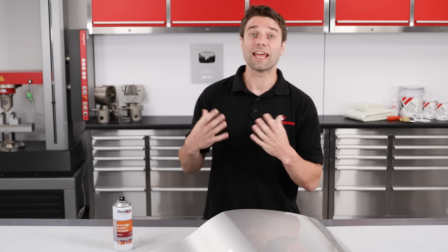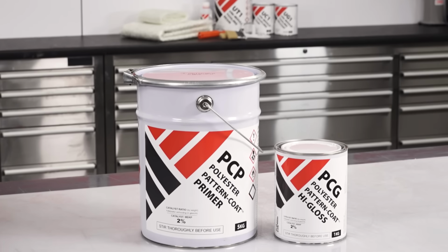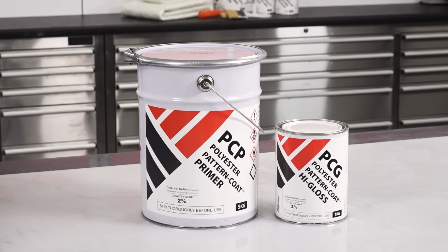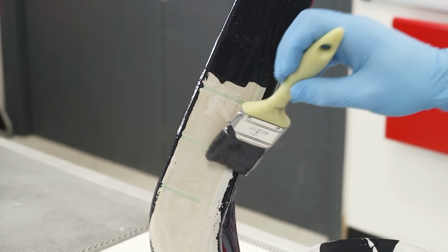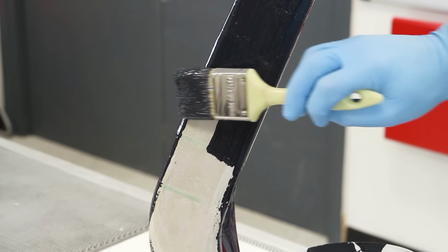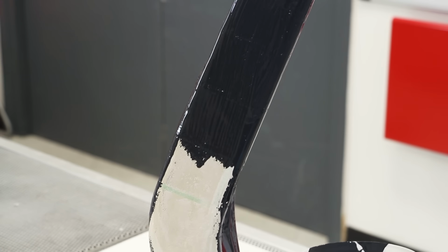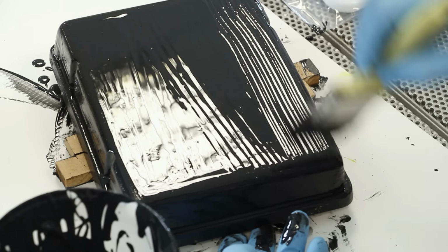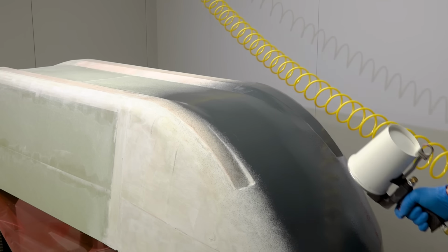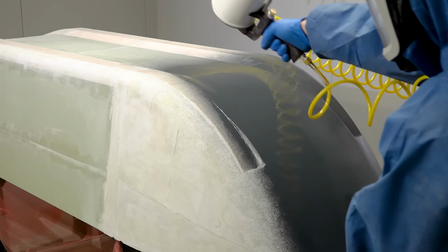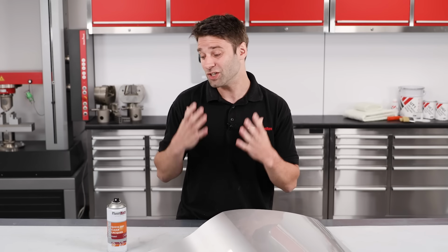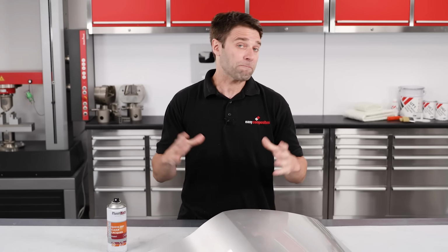If we now consider dedicated pattern coats like pattern coat primer and pattern coat gloss, as you would imagine, they provide a very stable and reliable pattern surface to any underlying material, be that model board, MDF, wood, metal, compatible foams, and so these are normally going to be the best choice for finishing new patterns or refinishing modified panels or parts. They also don't need an oven cure and can be easily applied by spray or brush.